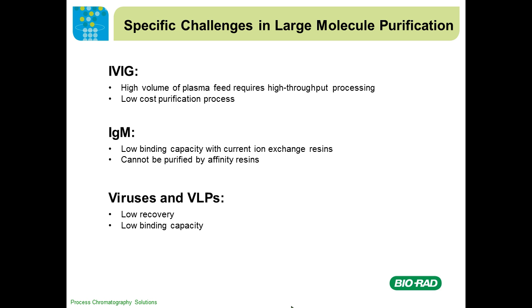For IgM, the main problem, as we mentioned, is that the molecular weight is so big, and therefore the diffusion coefficient is very low. And unlike IgG, where you are able to use protein A for the purification, there is no affinity resin available for IgM. Virus particles are even more difficult to handle in downstream processing, because with such a large molecule, if the pore size is not big enough, they are only able to use the surface for binding and capture. And if you have a large pore size, sometimes they are physically trapped inside the pore, so the challenge will be the recovery.